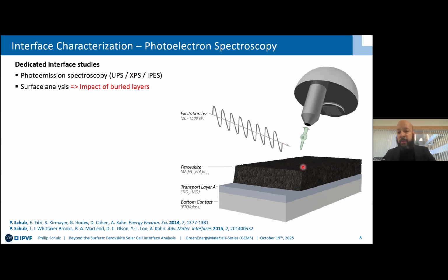In the schematic, what you have is, of course, the incoming photon beam that excites the electrons that are then emitted into vacuum, collected via the electron analyzer, set on trajectories corresponding to the kinetic energy that is coming from information about their binding energy in the solid, and then projected on the detector. So the entire measurement is dependent on the electron leaving the surface in an unperturbed state. And this is also where the limit of the application is. It's a very surface-sensitive technique.